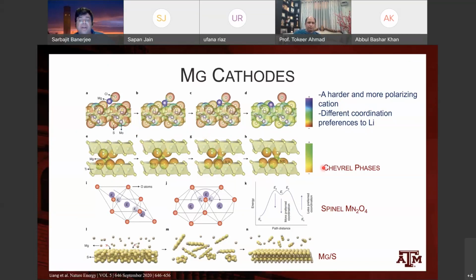These molybdenum sulfide Chevrel phases have been excellent because magnesium is a hard ion based on Pearson's hard and soft acid-base principles. Sulfide being a relatively soft ion is readily distorted as magnesium moves through this lattice. All of the oxide lattices have been less amenable to magnesium diffusion. So there's some work on spinel manganese oxide, MgMn2O4 systems. And again, there's some work going on also with the magnesium sulfide systems.